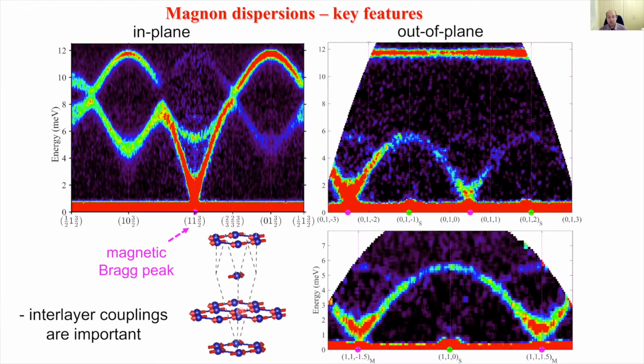And then we can also probe the direction vertically up. And then we can see that, say, starting from a magnetic Bragg peak, there's also strong dispersion in the interlayer direction, indicating that the interactions are comparable, are important both in the layers and out of layers. Now, an important property that we see is that the spectrum has a very small gap, finite but small, above the magnetic Bragg peaks, as you can observe it here.